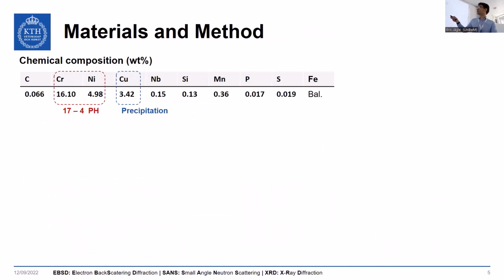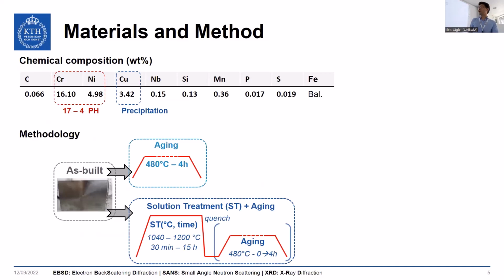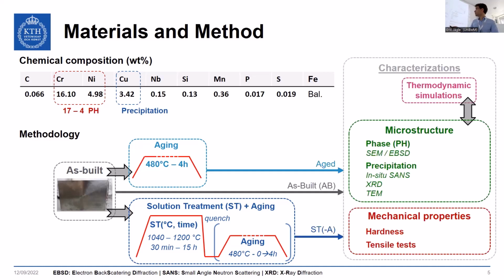So here I just put the material. It's 17-4 PH because of 17 chromium and 4 nickel, more or less. Here you have a high copper composition for precipitation of these nanophase copper precipitates. Our methodology was to apply different thermal treatments, starting from the as-built, then aging at 480 for up to 4 hours, or dual thermal treatment with first a solution treatment at high temperature with different temperatures and times, and a subsequent quench, and then subsequent aging at 480 for up to 4 hours. All this will be compared in terms of microstructure and mechanical properties, with hardness and tensile tests. The microstructure is also compared to thermodynamic simulation that has been done, but I'm not going to present much of this in this presentation.